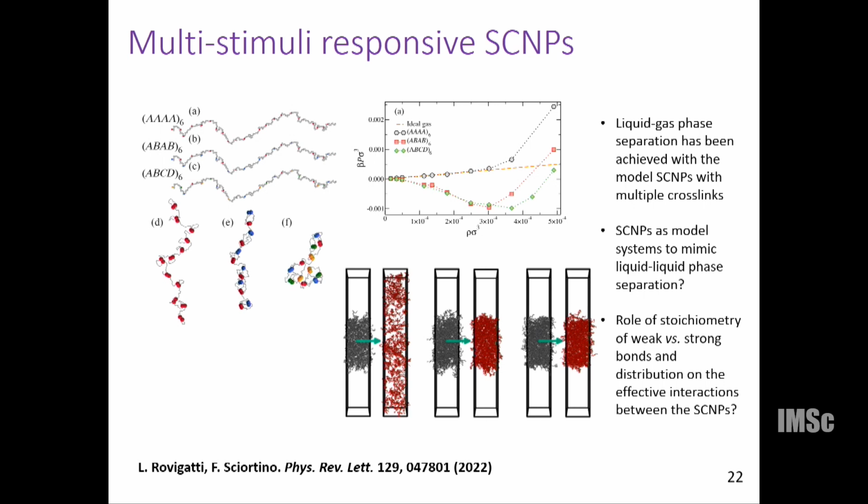In this work, what is found is that if you increase these different types of reactive monomers, the kind of structures you get are more compactified, simply because of the same contour distance logic. They need to find their partners at longer distances, so they fold more effectively as compared to the homo cross-linking case. If you look at their phase behavior, these are the equation of state diagrams for all A, AB, ABCD, and you can see that pressure is negative in these two cases. That means there are attractions coming from combinatorial entropy, which I have shown before.